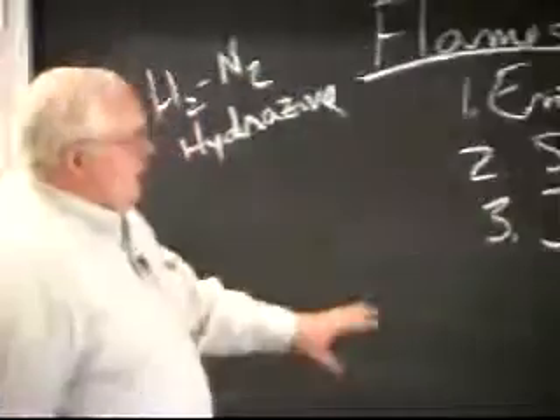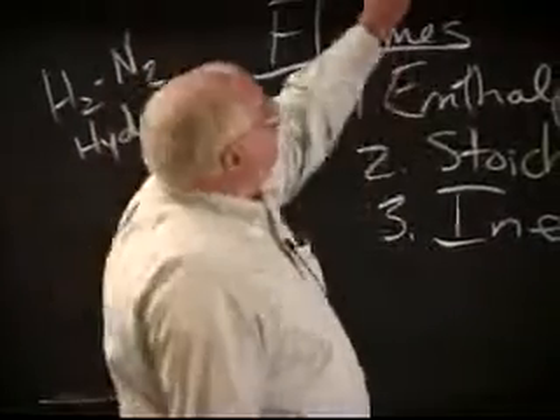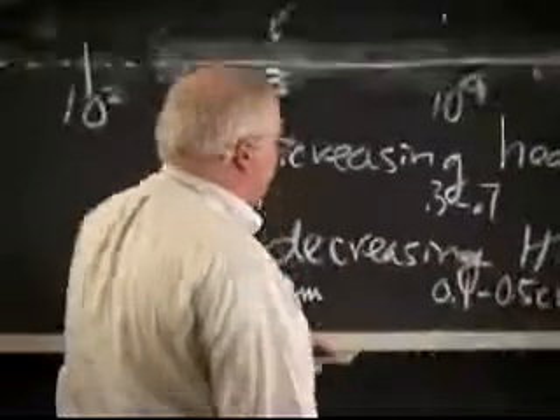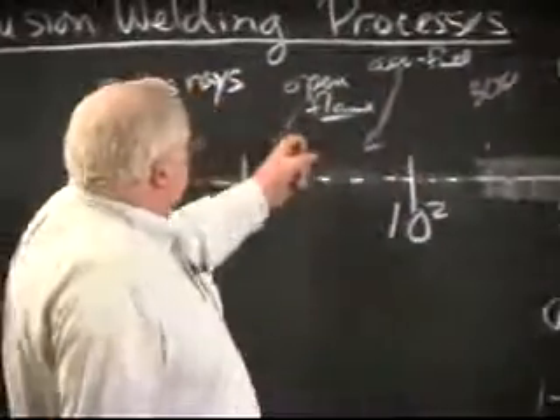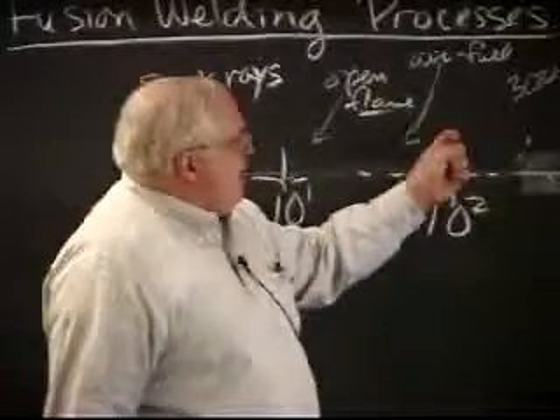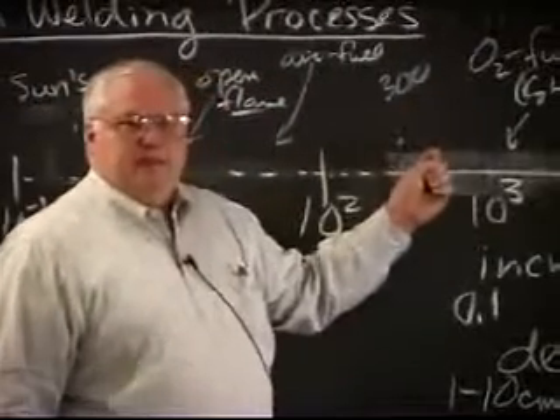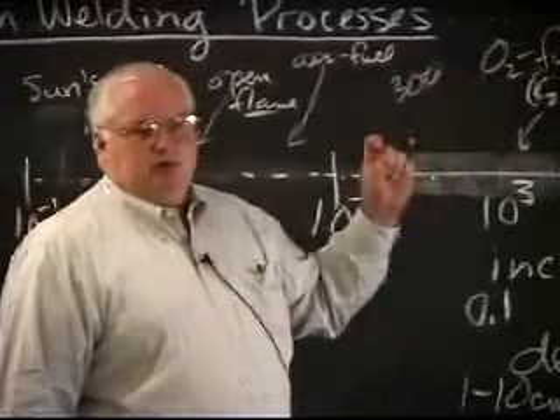In any case, that also means that an air fuel mixture, if I go back to this over here, has about an order of magnitude lower heat intensity than an oxy-fuel mixture. If I use pure oxygen to burn and have no nitrogen around, I can get about 10 times the heat intensity. Now, it's not really 10 times the temperature, it's only about double the temperature. But for other reasons that we'll go over next time, the combustion intensity is a complex function of the temperature, the velocity of the gas, and other things. But we'll cover that next Wednesday. Thanks.